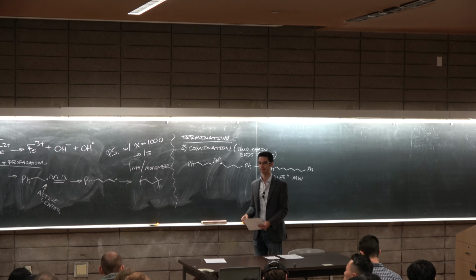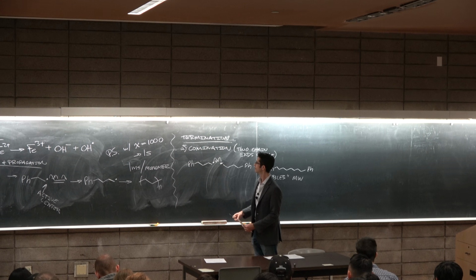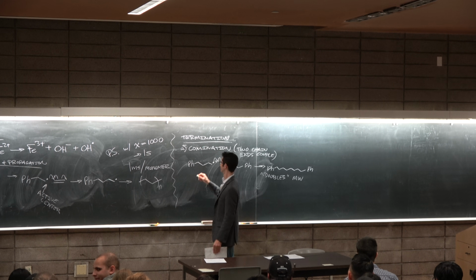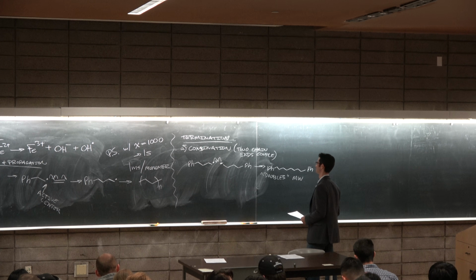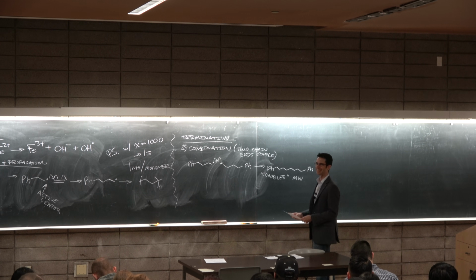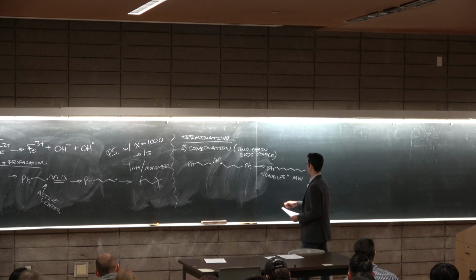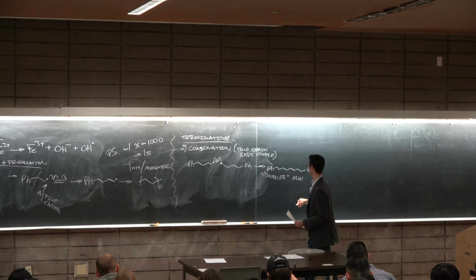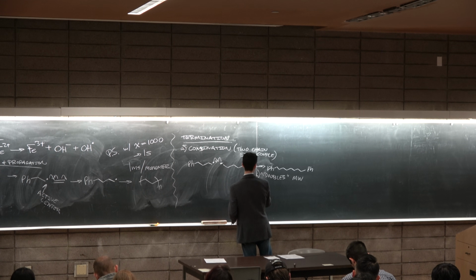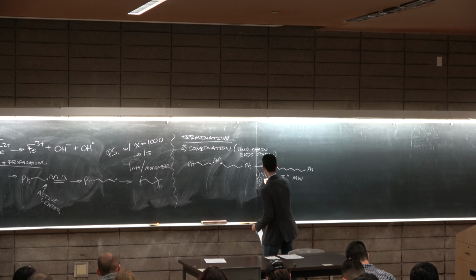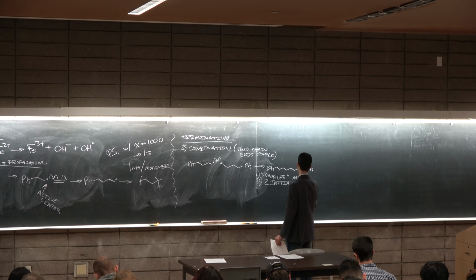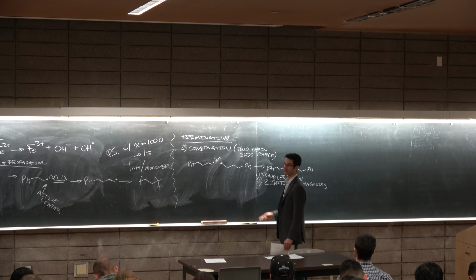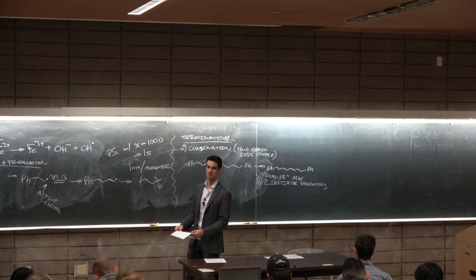Yeah. Clarify, combination, not combination. You'll pay for that. Yes, combination. This doubles the molecular weight, and you have two initiator fragments. So spectroscopically, you might be able to tell what was the product of combination.